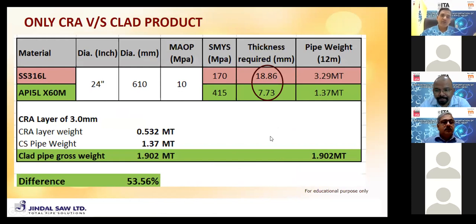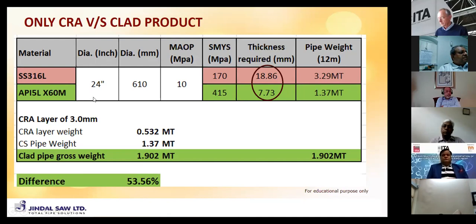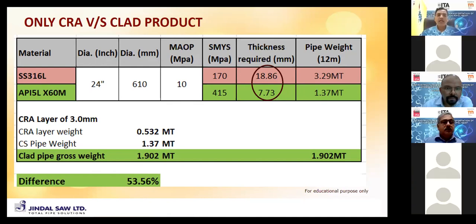Say, for example, if we use only CRA, which is say SS316, and suppose there is a line of 24 inch with a maximum allowable operating pressure of 10 MPa, we require a thickness of 18.86 mm, while if it is API X60M grade steel, we require 7.7 mm of thickness, and then you can see the weight difference is huge. If we use this carbon steel along with a CRA layer of 3 millimeter, the gross weight will come around 1.9 metric ton. So there is a difference of around 54% by weight. So definitely this is a huge saving which can be considered during the decision of the material which can be used.